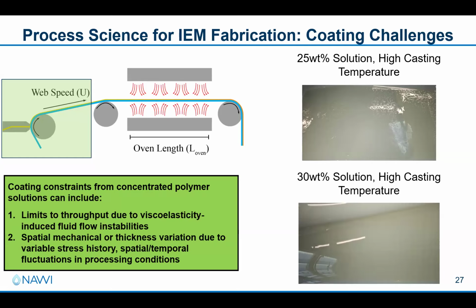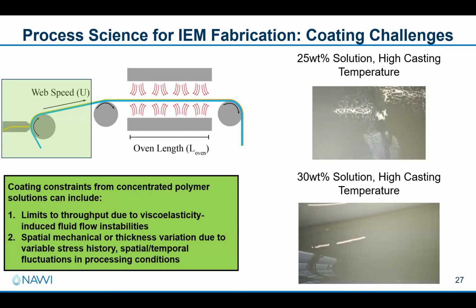But what we see here in the top image, at a 25 weight percent solution of BPS that we've dried to make an ion exchange or a cation exchange membrane, is that you can get these pinhole defects that are much more severe than the orange peel defect blown up here. While the orange peel defect is undesired, these pinhole defects comprise a complete failure of the membrane. Where if we go to higher solution concentrations and still maintain high casting temperature, we can get very smooth, fairly thick coatings.